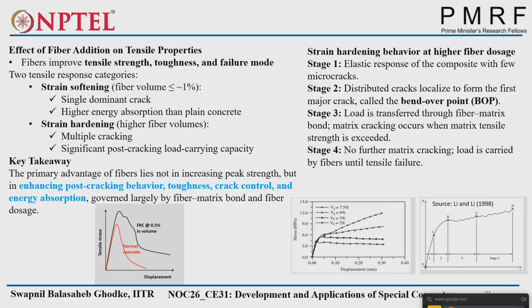Yeah, it will not fail in tension, but I hope I will show one image after the lecture. So the beam will not exactly crack. It will not exactly break down. Too much energy absorption happens because of the fibers. Suppose the bottom fibers break down in tension, the fibers available above will resist. Then if those break down, the ones above that. So it is a continuous process of widening of the cracks until all the fibers in that matrix go through breakdown.